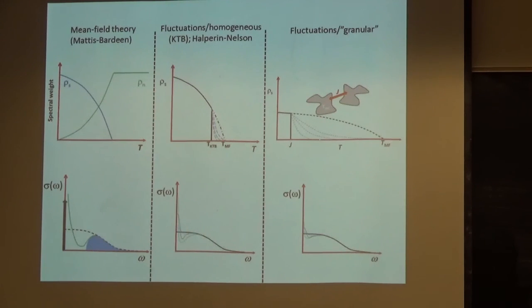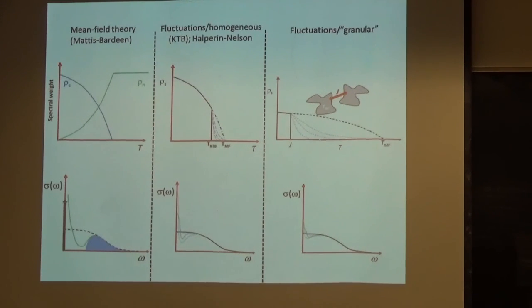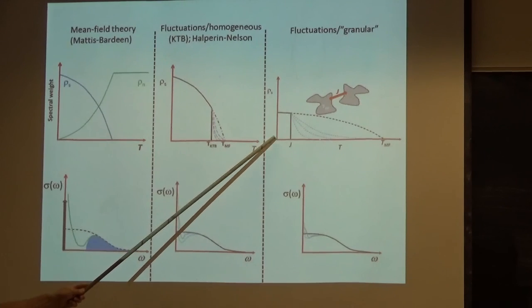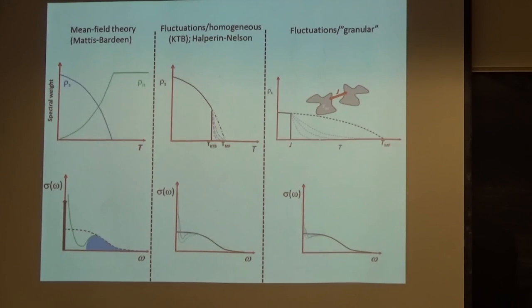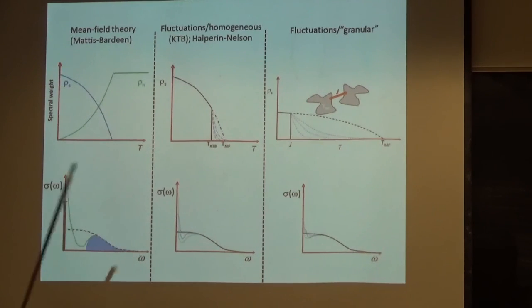So the superfluid density that I would write down in my notebook, I'm now going to measure the superfluid density, but I'm going to set my signal generator at 1 kHz. But in the next room, there's another person who's measuring it at 10 kHz. They're going to get a different kinetic inductance. So in this anomalous region, the value of the kinetic inductance, or the inertia of the superfluid, whichever way you want to look at it, is a frequency-dependent and length-scale-dependent phenomenon, where it's not in the superconducting state. So that's basically what I'm saying: this is rho s of omega.